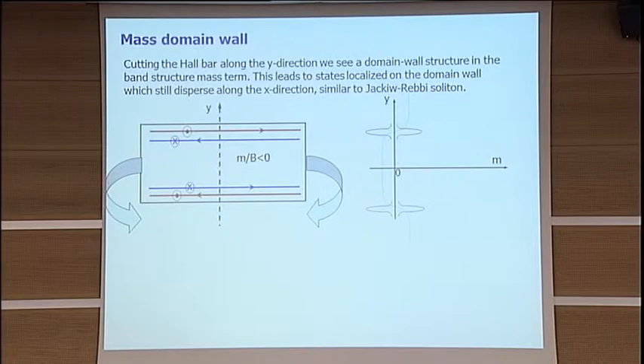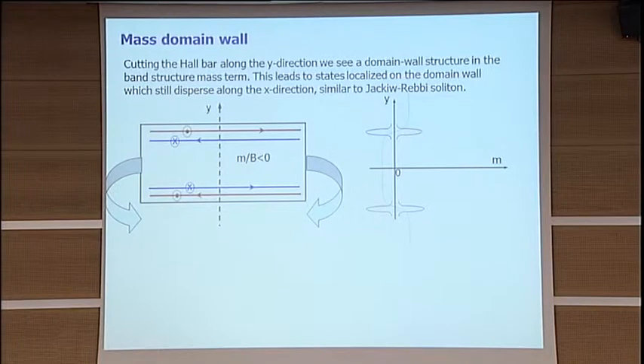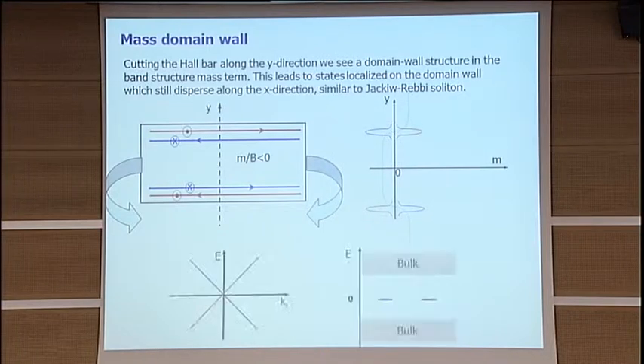If you tune into the regime where the two-dimensional bands are inverted, you have mass less than zero. In this case, the sample boundary looks like a domain wall of the Dirac mass — outside you can take the Dirac mass to be positive, and inside, in the band-inverted regime, which occurs when the mercury telluride layer is greater than 6.2 nanometers in thickness — something we can predict very accurately theoretically — the sample boundary looks like a domain wall that traps bound states.